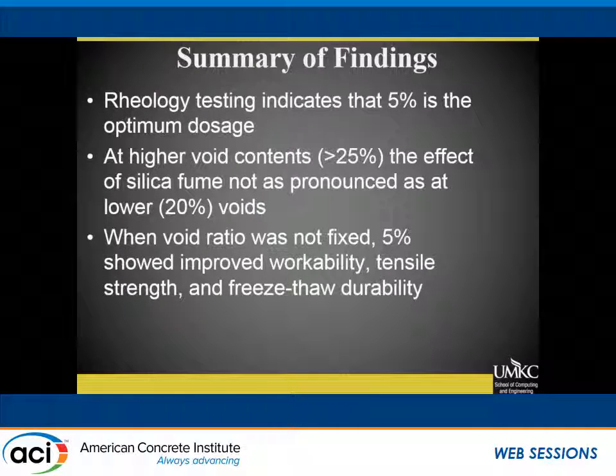So all right, summary. Rheology says we got something happening around 5%. I'll buy that, as it supports what we've seen in the field. At the higher void contents, 25% and above, we didn't see much difference. The concrete wasn't really strong enough to have good precision, and so we had quite a bit of similarity, but a big range in precision. At 20%, so a little bit stronger, we were able to see differences.